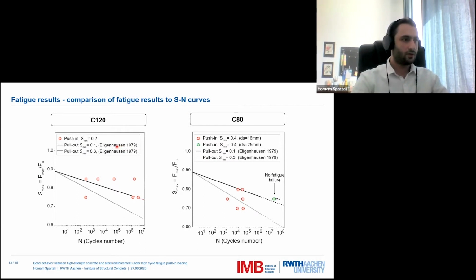Here's a comparison between our fatigue results and the SN curves that are provided by Eligehausen, who did a lot of pull-out tests. To indicate here that in our case it is push-in, in his case pull-out, but here's a comparison. We applied 2 maximum loading levels in the case of concrete C120. You can see that actually we had a large scatter. So for the same load level, you may have a couple of hundreds of cycles, or you also may have more than a million cycles.